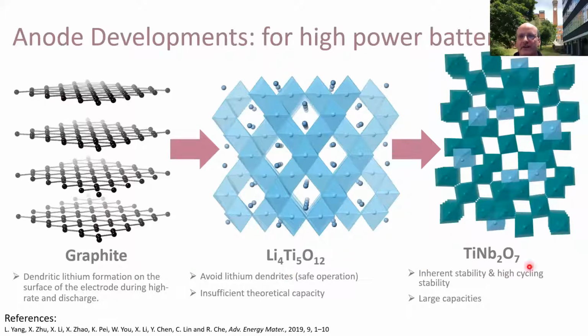And so the ones that really attracted attention are these niobium containing materials. I've given one here, this titanium niobium oxide, but there's a whole host of these materials that have interesting so-called shear structures. Hopefully you can see some corner linking of octahedra, and then you have this edge sharing of octahedra. These are so-called crystallographic shears that stabilize the structures. And these are highly stable materials. They're excellent for insertion and removal of lithium, and you can do this at very high rates. So you can start to think about charging your battery in 6 minutes or less with one of these materials.